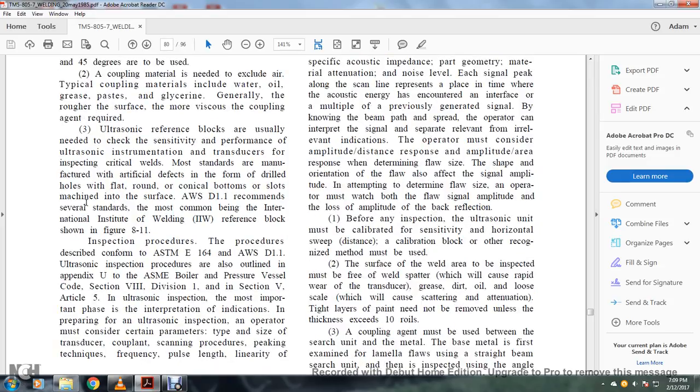An ultrasonic reference block is usually needed to check the sensitivity performance of the ultrasonic instrument with the transducer for the inspection of critical welds. Most standards use artificial defects in the form of drilled holes in the flat, round, or conical bottoms of slots machined into the surface. The AWS D1.1 recommends several standards, the most common being the International Institute of Welding reference block shown in figure 8.11.